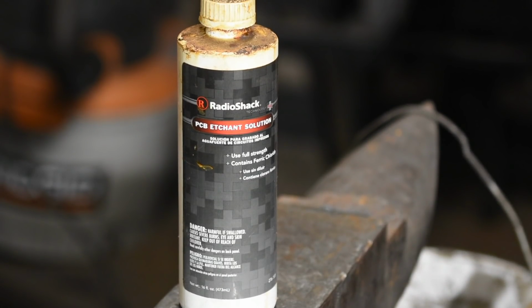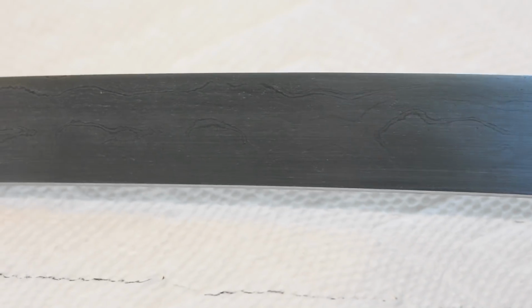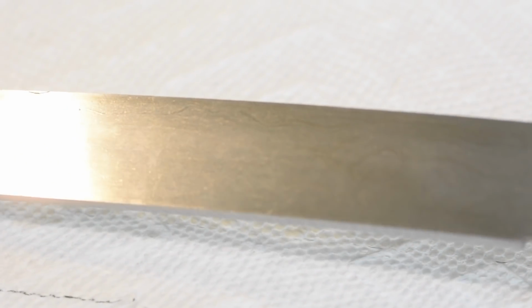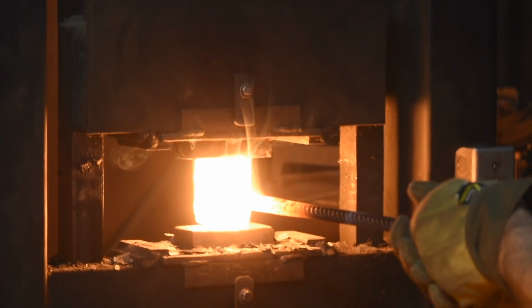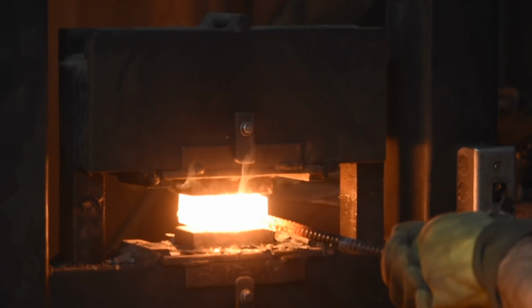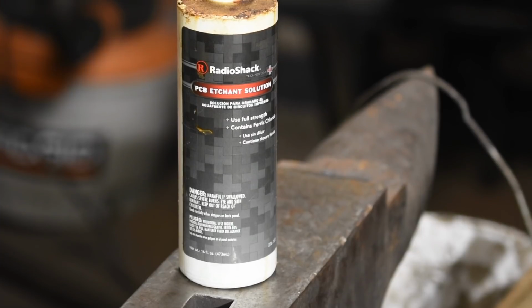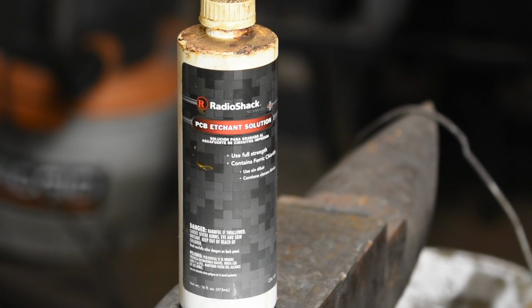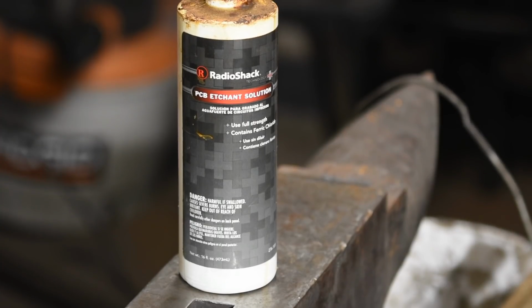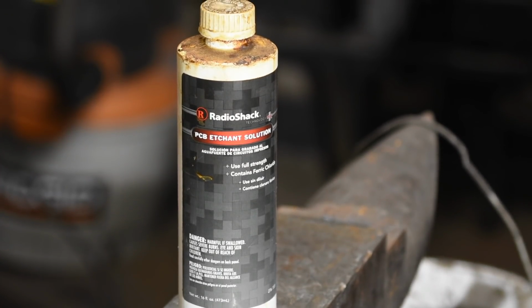Incidentally, if you're curious why I wouldn't be using ferric chloride, ferric will get into the little tiny nooks and crannies that are produced by forge welding tons and tons of times like you do with traditional Tamahagane-based steel. It'll eat holes into it. The ferric's likely to stick in those holes and just wreck the thing. So you really don't want to be using really aggressive etchants like that.